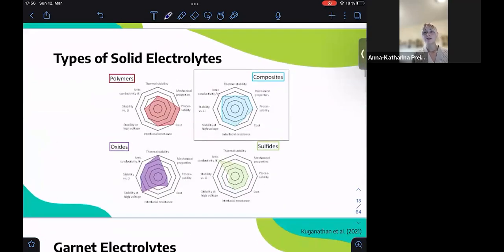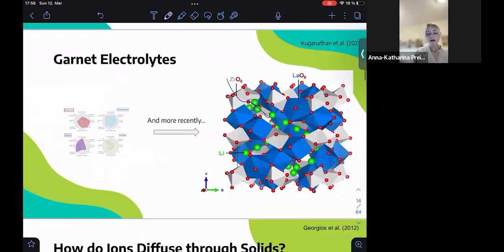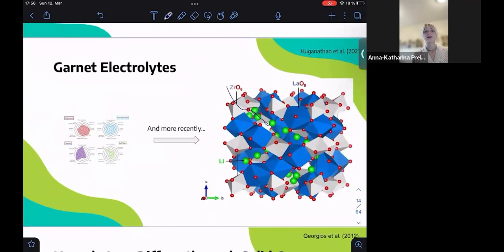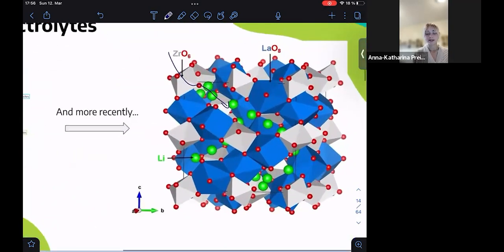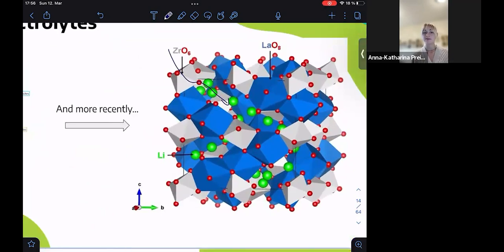In addition, we have composites, which are some combination of polymers and ceramics, where researchers can tune the characteristics that they want. Also, a special mention to garnet electrolytes, which are a family of ceramics. The one I'm showing here is Li7La3Zr2O12, which has a high degree of order and symmetry, with the oxygen octahedra forming a network of interconnected tunnels that allow the lithium to pass through more easily.